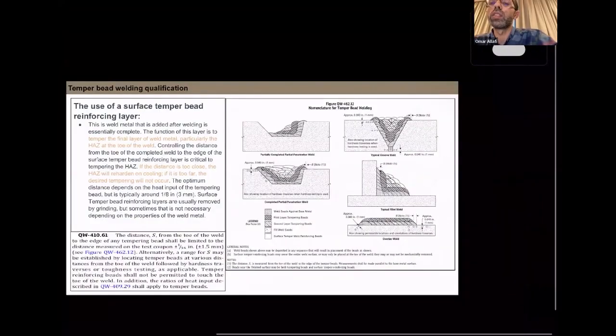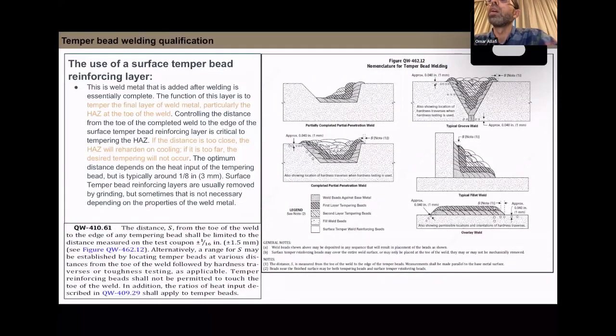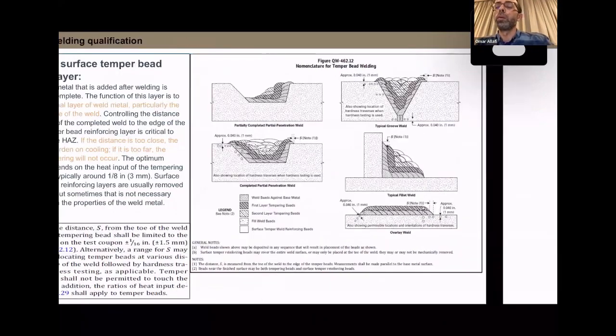We are adding this to temper the subsequent weld, and sometimes it can be removed. The surface temper bead can be removed. Removal of surface temper bead is not an essential variable, but it is required in some codes and standards. This distance here is within 1.5, and within 1.5 requires no qualification, but usually it should be between 2 to 4 mm.